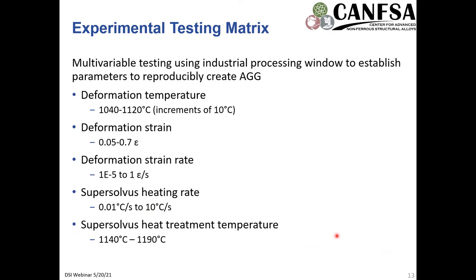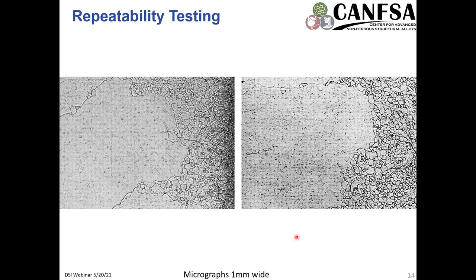And so the test matrix of things that we were looking at were deformation temperature, deformation strain rate, as well as the supersolvus heating rate and supersolvus heat treatment temperature. We explored all of these regimes, and there are dozens, if not hundreds, of samples that we went through trying to explore this. In repeatability testing, here are etched light optical results of the specimen showing very large gamma grain growth into and consuming neighboring gamma grains. So we were able to not only create abnormal grain growth, but reliably reproduce it in consistent regions of the material. This was a very critical step in the project to establish a point where we can then work forward and explore the microstructure and the response to different process conditions.